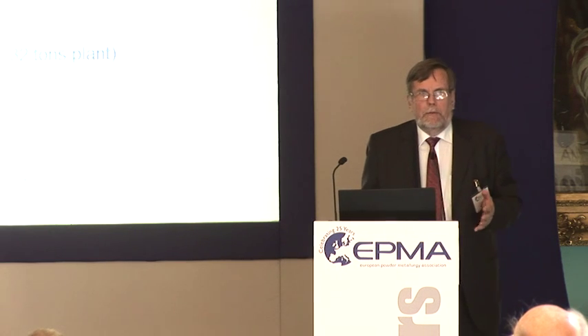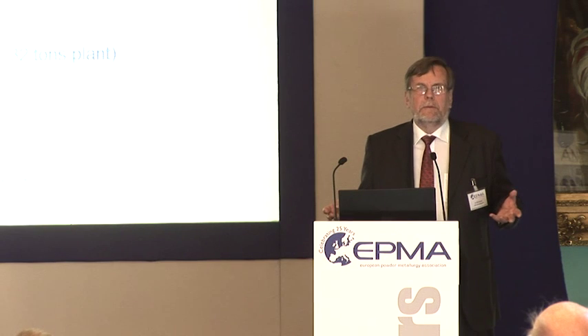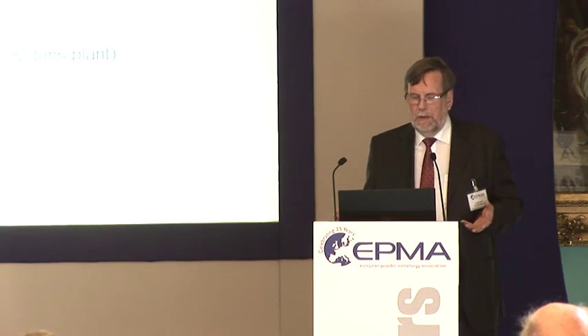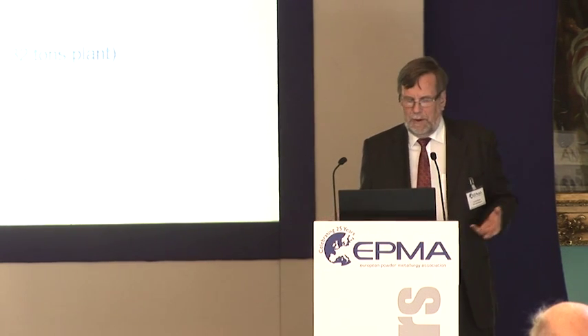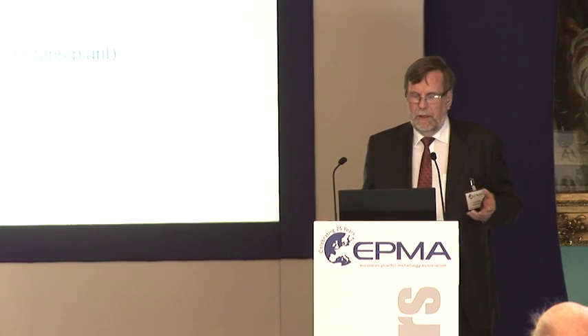Regarding HIP development, the HIP units are now quite large. The largest can take a load of 30 tons, which is impressive. Cycle times have decreased from 24 hours to less than 12 hours. The number of cycles has increased per year. The process control has improved.